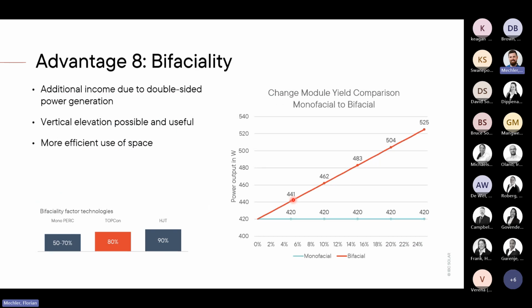And the last topic, it's the bifaciality. Bifaciality means that not only the front side produces energy, also the backside produces energy. But there is an issue with the backside because the backside cannot produce the same energy as the front side. That means it depends on the technology of the cells, how much the backside can produce in comparison to the front side. For PERC, it's like 70% of the front side, which the backside can produce. For TOPCon, it's 80%, and for heterojunction, it's 90%. So with the ES10 module, the backside can produce 80% of the front side.